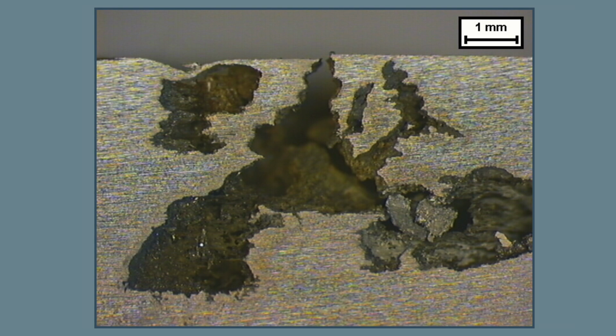So the discoloration, when you're welding, you have those tint lines. So a similar thing happens with corrosion. Your passive film is changing, so it leads to discoloration. The pits were so small, but if we go to the next picture I sent you, you could actually see how catastrophic the pitting was. So from the pinhole at the top, we had excessive damage and corrosion of the material underneath, which was quite extreme. That is absolutely terrifying, actually, that really what's on the surface belies what is happening underneath.